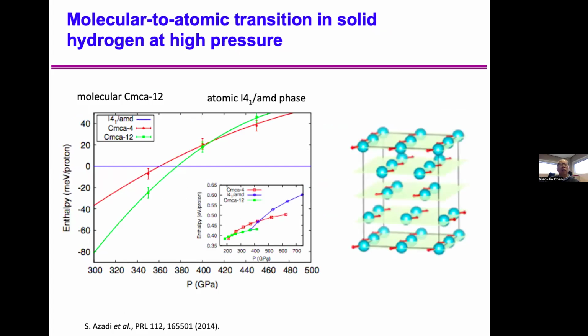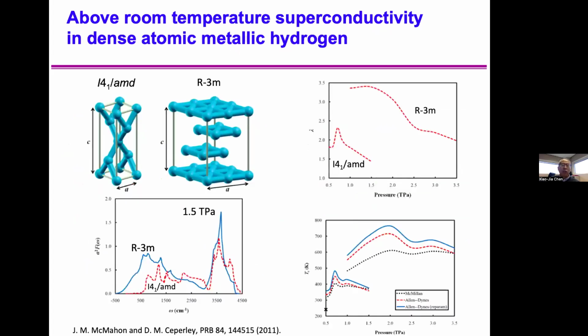Here are more reliable calculations. There's a phase transformation from molecular to atomic phase at very high pressure. You can see the molecular space group is Cmca, but in the atomic phase, I41/amd. The calculation also shows that in either the molecular phase or the atomic phase, Tc is really very high, like above 500 Kelvin. However, this is really hard to get, a metallic state.